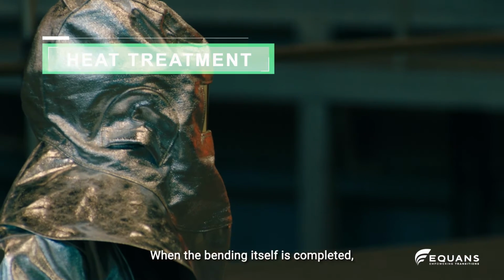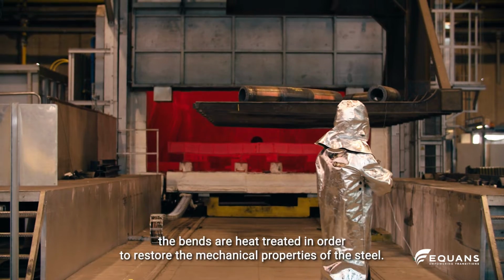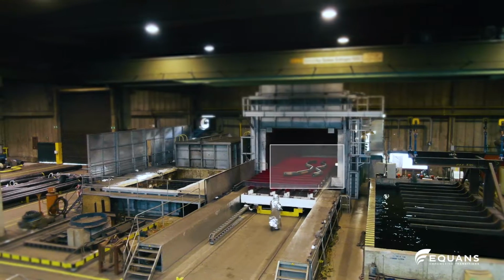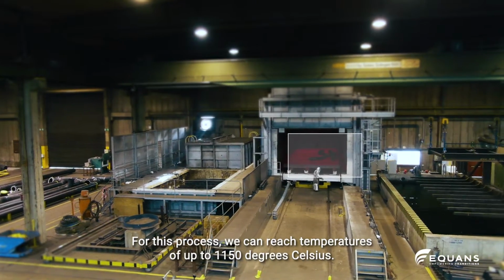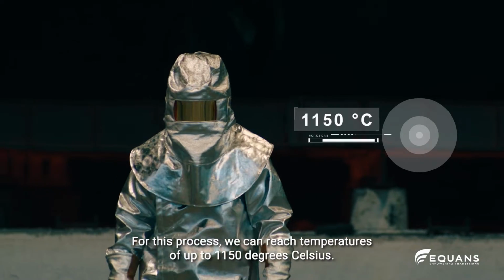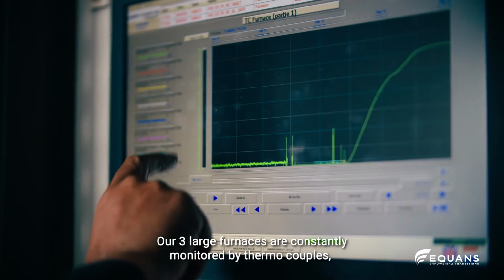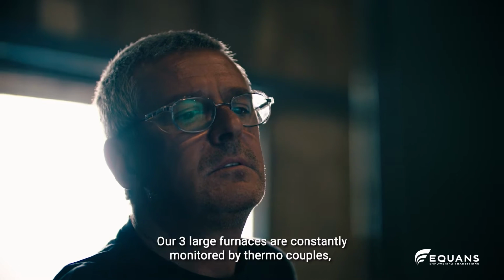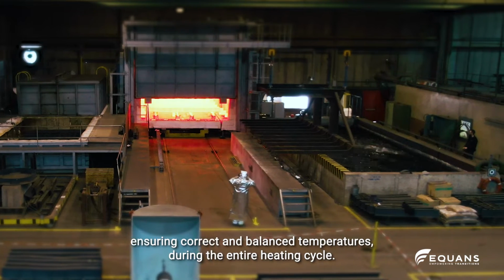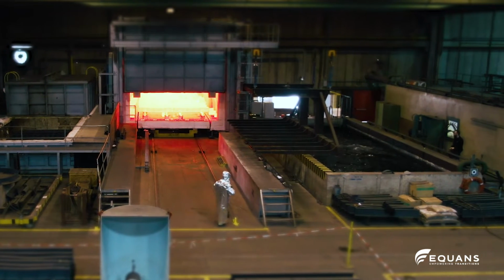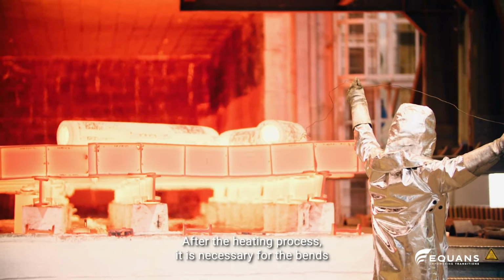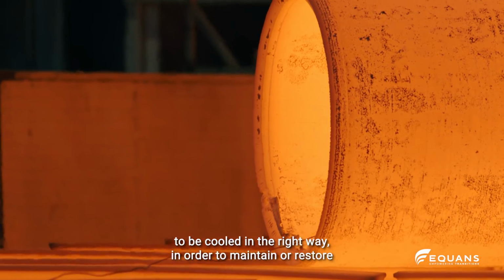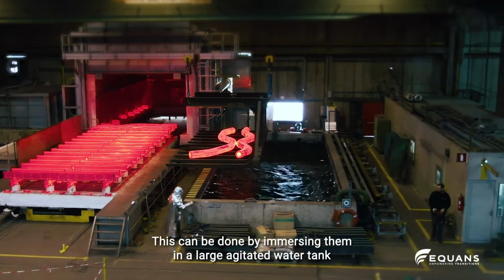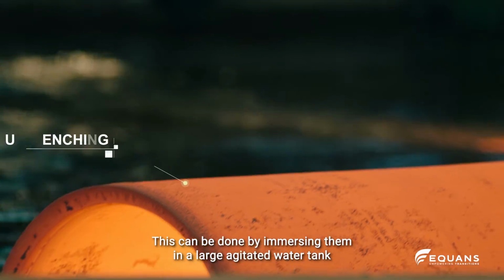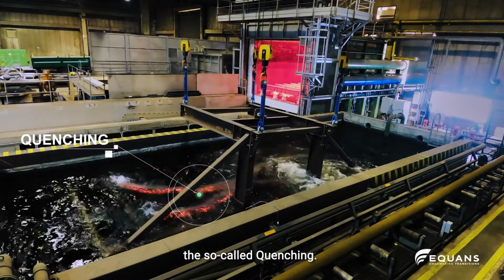When the bending itself is completed, the bends are heat-treated in order to restore the mechanical properties of the steel. For this process, we can reach temperatures of up to 1,150 degrees Celsius. Our 3 large furnaces are constantly monitored by thermocouples, ensuring correct and balanced temperatures during the entire heating cycle. After the heating process, it is necessary for the bends to be cooled in the right way, in order to maintain or restore the mechanical characteristics of the material. This can be done by immersing them in a large agitated water tank, the so-called quenching.